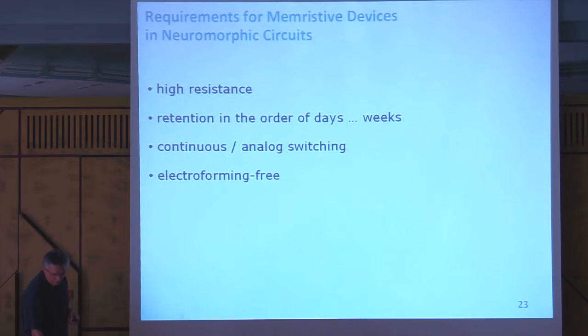Let's go for that. So what we like to have for neuromorphic engineering is a high resistance for low power consumption, retention times in the orders of days or weeks. That's an interesting point, because in RAM application you like to have storage over years, 10 years for example in your memory stick. For neuromorphic applications it might be not necessary because also your synaptic memory changes with time. So it depends very much on the topology and the circuit whether you do need weeks, days or whatever. So it's not necessarily the case that you need a retention over years or longer. Even days might be an interesting point. We like to have a continuous and analog switching and of course no electroforming in the beginning of the process. So the device should work from the beginning.